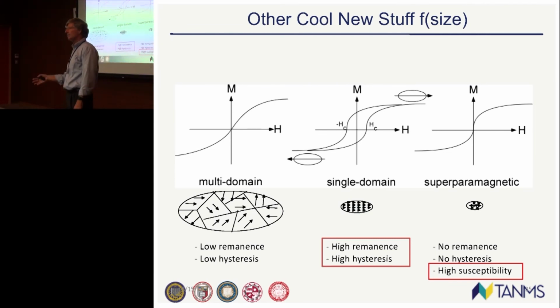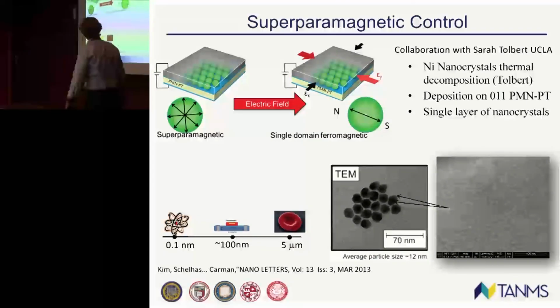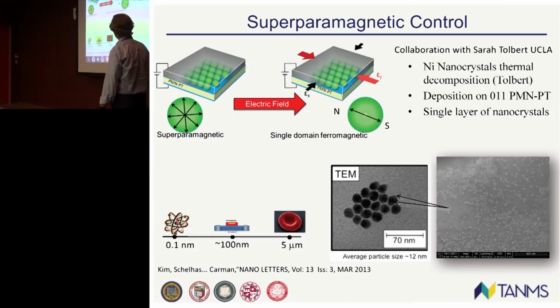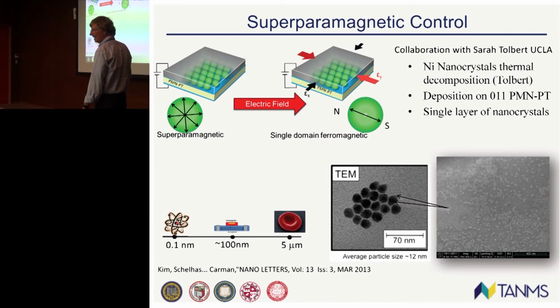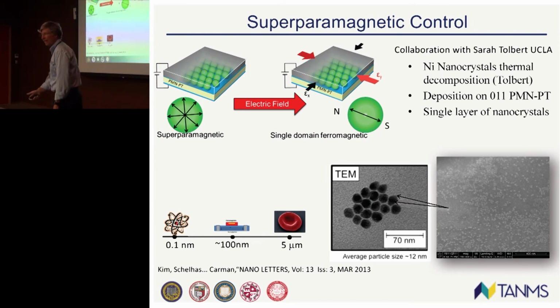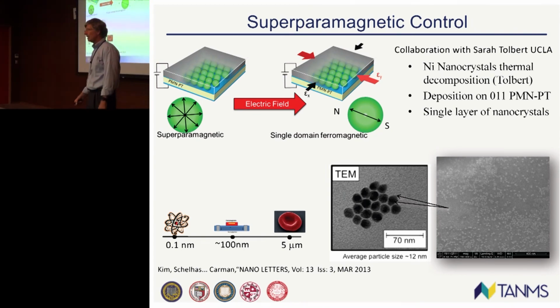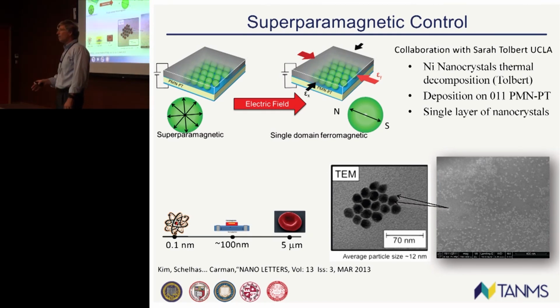So we said, well, wait, maybe we can electrically control anisotropy at one temperature. So we got together and said, well, we can start off with a superparamagnetic particle. We can put it on PMN-PT. We can actually apply an electric field which will strain this, and we believe we could stabilize the superparamagnetic into a single domain ferromagnetic structure. So at one temperature, we can turn on and off superparamagnetic behavior. Now to do that, we made nickel particles. Once again, all this is about nickel, on the order of about 10 nanometers.